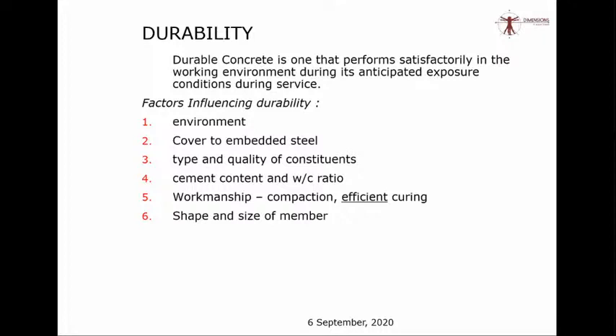If you have reinforcement inside, and if the quality of reinforcement is not good, or if the reinforcement inside starts corroding and swelling, then also the durability of your concrete is gone. And the reinforcement is protected by properly giving proper cover thickness. Therefore, the kind of tolerance you have maintained while giving cover thickness is important. The quality of concrete in the cover is also very important.